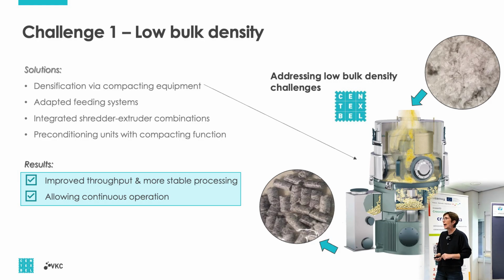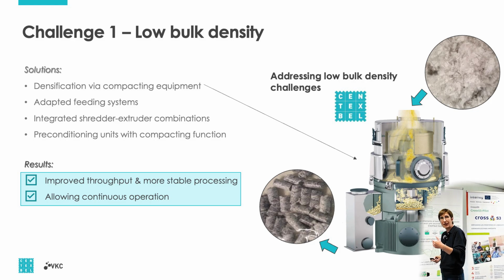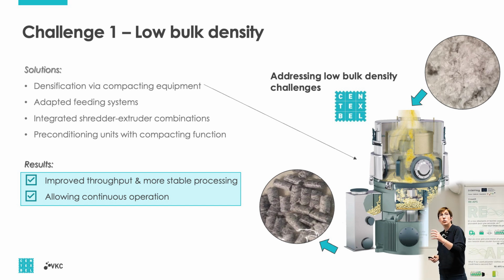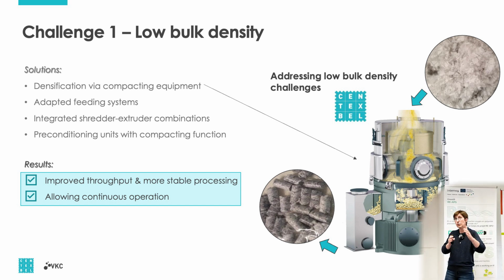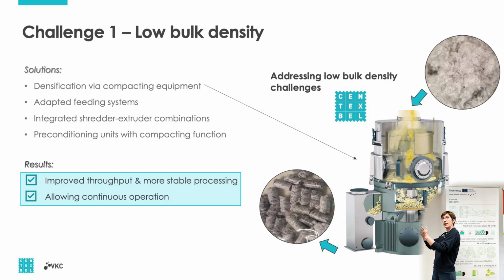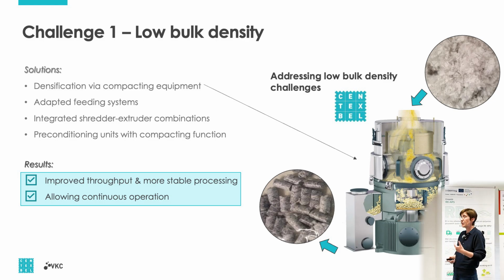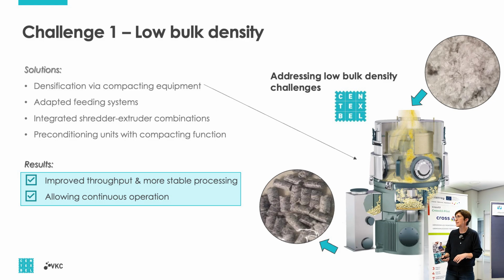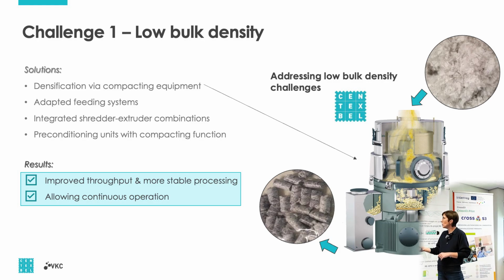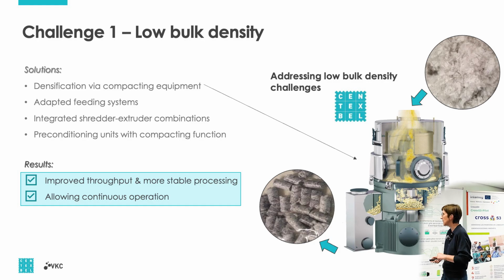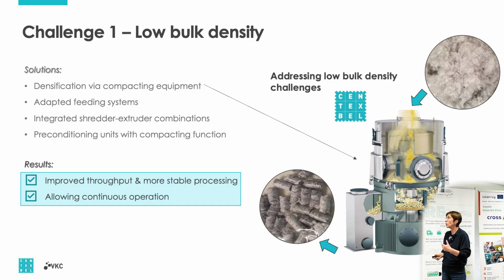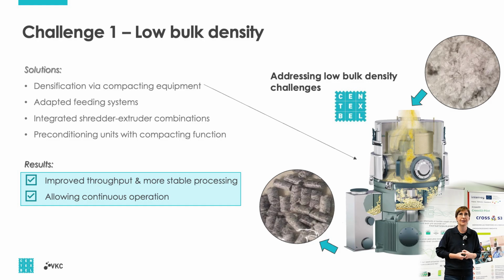So what you can do, you need to densify those materials. And I will later on show you, when talking about industrial implementations, that some machine builders are really focusing on it. They try to, in one step, shred and densify those materials into the extruder. If you don't have these options, you can work with a separate step. And this is an example of a kind of compacting unit where you start from a fluffy material and you use mechanics, so you don't melt your material, to avoid some kind of breakdown of your polymer chains. You just try, with some mechanical force, to squeeze it into a pellet-sized structure, and that's easy to dose.